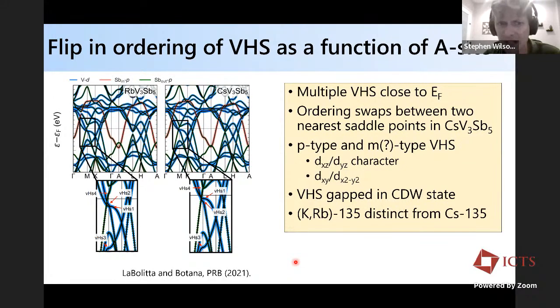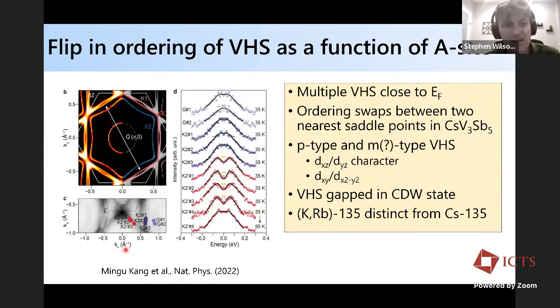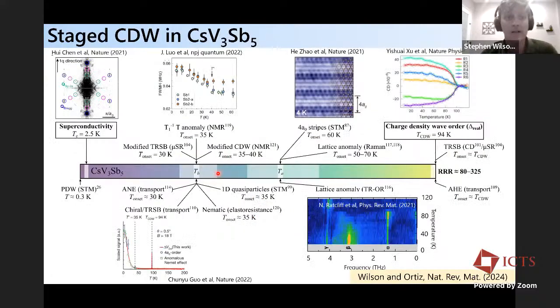Okay, and I just want to further highlight, this is some photoemission work from Riccardo Comin's group, where they basically look at one of these Van Hove singularities, I believe the one with XZ and YZ character, and they can see that this is the one that's gapped as you go through the charge density wave state. Okay. Now, the cesium system has this just kind of much more complicated charge density wave state.